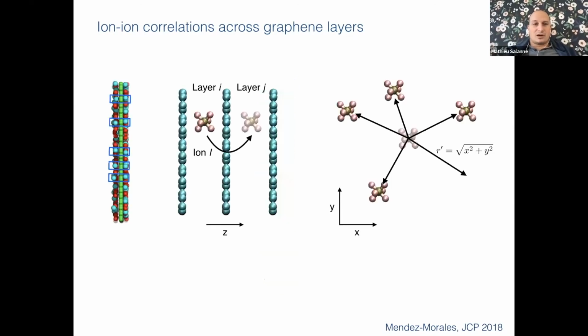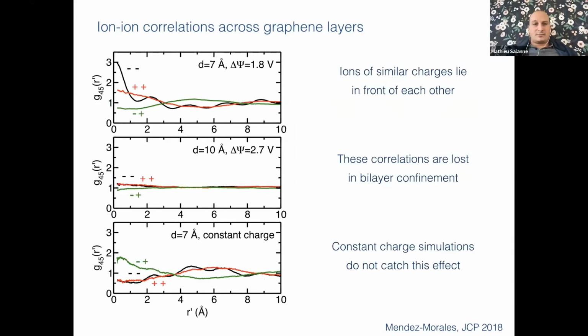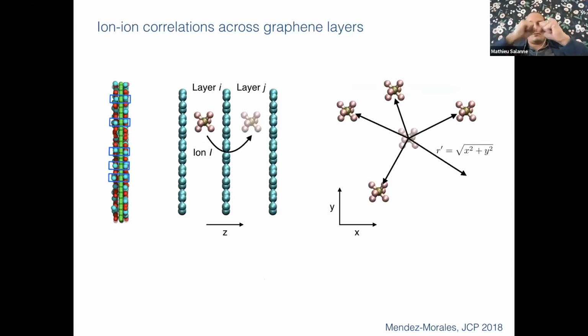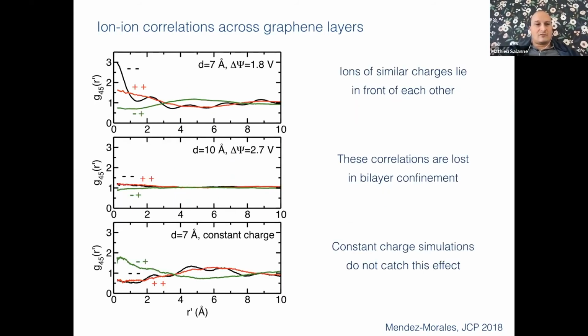And so we try to characterize this further by computing some radial distribution functions. So what we do is that we project an ion from one layer to the other, and then we compute its distribution function with all the ions. And what we see is that we have this kind of funny correlation: you have a peak for same-charge, cation-cation and anion-anion, interactions at distance 0, because of course that's a projection which is in front of the underlying ion. When you have the 7 angstrom pore, you lose this when you have the 10 angstrom pore because of the bilayer arrangement. You don't have this any more.